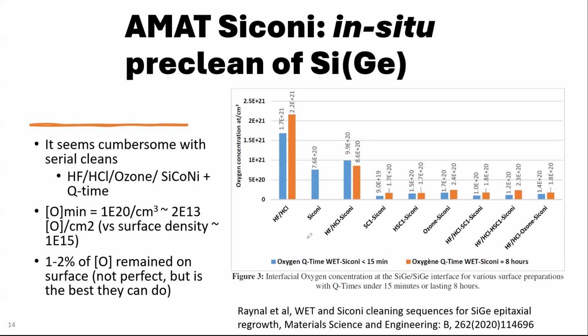So you have to do in situ. And so if I do in situ, meaning that it's inside the chamber of the high K, can I avoid HF in this process? No, you cannot. If you do Siconi by itself, it's still high. You have to use a combination of everything. So they went through three wet benches, HF, SC2, SC1, and then Siconi. And you may have to add in something to make it even better.